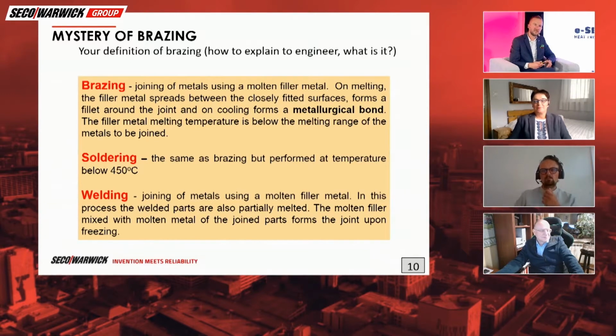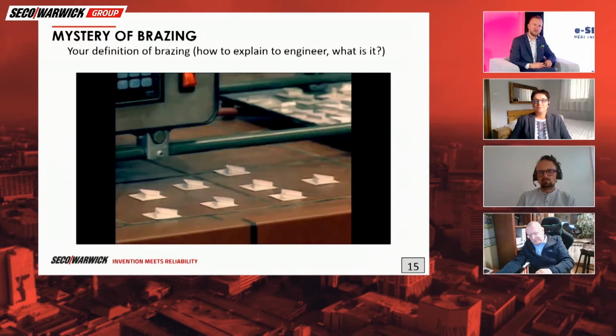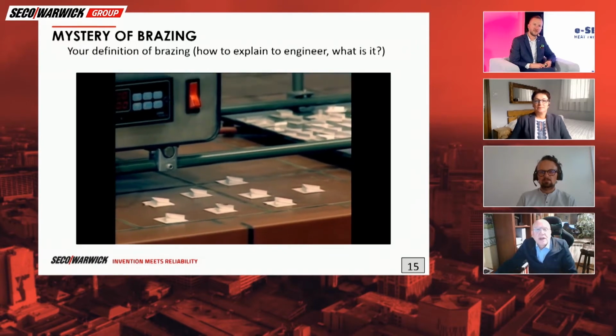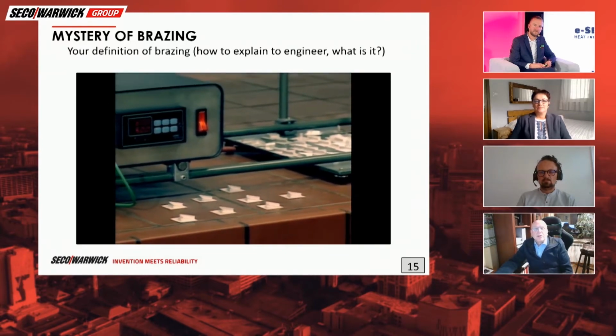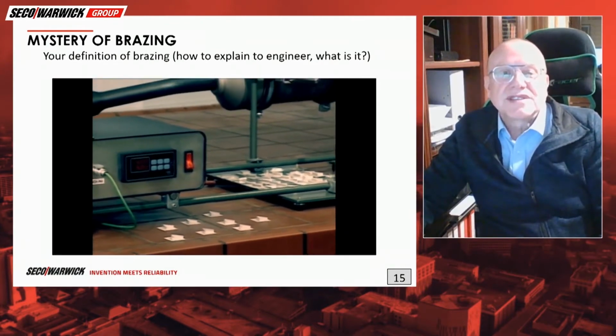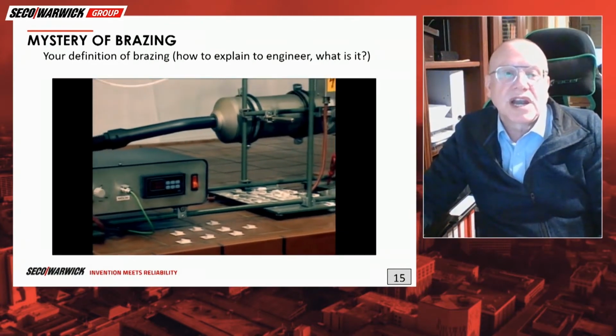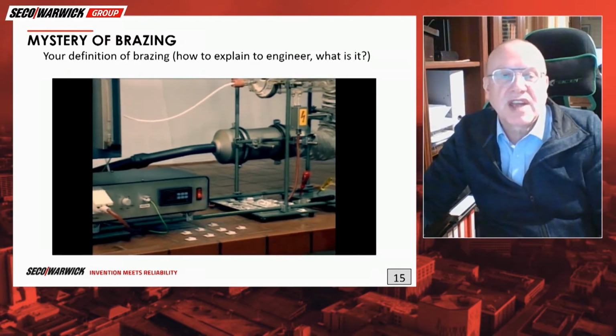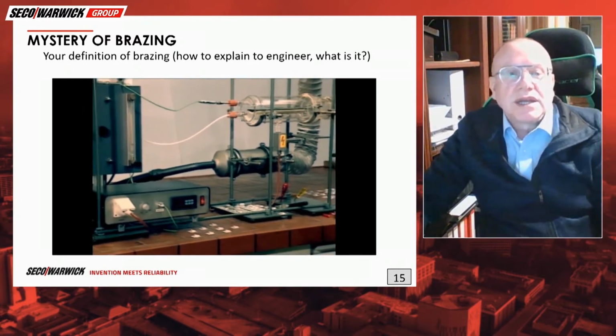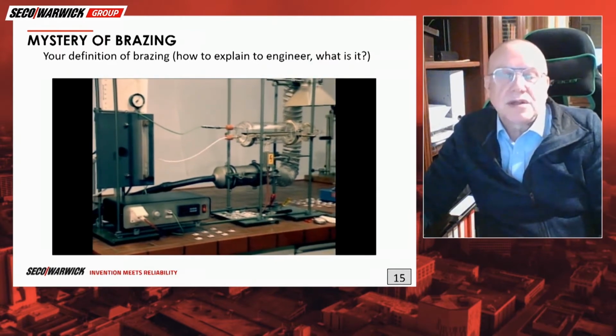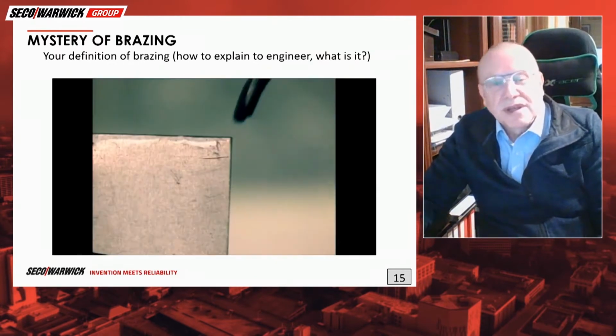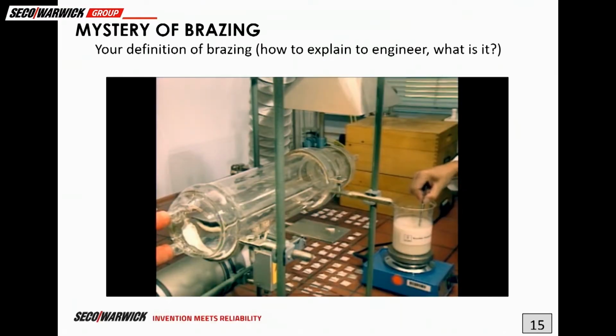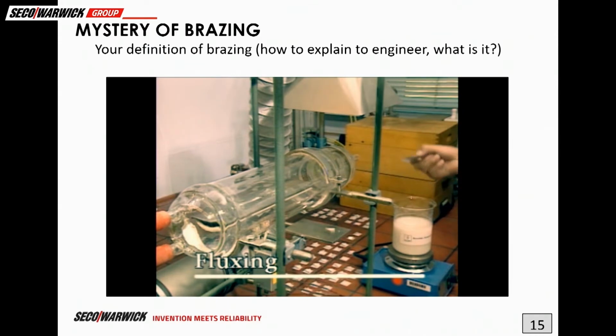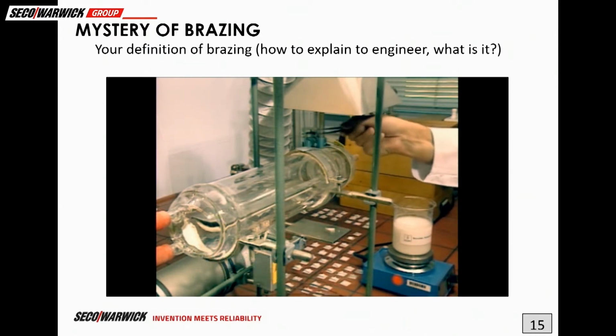But before this discussion, I received a nice movie from Leszek. So let me show you the movie. And Leszek, if you can explain what we see in the movie right now. Okay. In this movie, we are going to show how two elements are brazed. A small coupon, square-like, 20 millimeters by 20, with an angle. And for that process, we must also use flux, because flux is a factor which cleans the surface, which prepares the surface for the filler metal to flow freely.